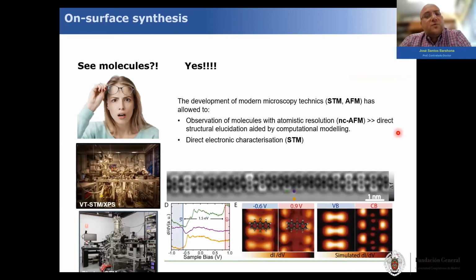Moreover, we can not just see the structure of the molecule, but also we can characterize the electronic structure by using the STM tunneling microscopy, by applying a bias with a tip on top of the molecules, and we scan all the surface. We can find where the different orbitals are located. So when a given voltage is corresponding with the energy of that orbital, it shines like this bright yellow color. So we can obtain both the HOMO and the LUMO of our molecules. So these two tools are a very, very powerful resource to characterize molecules both structurally and electronically.